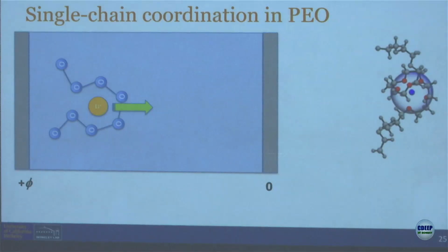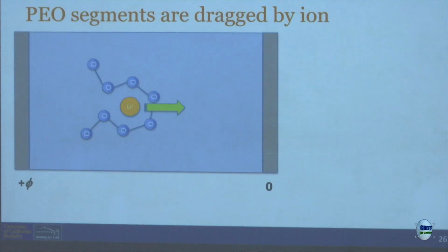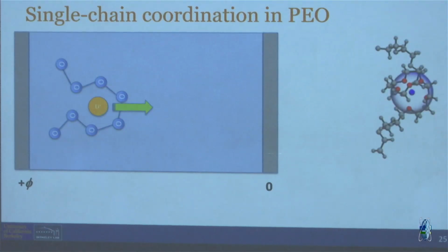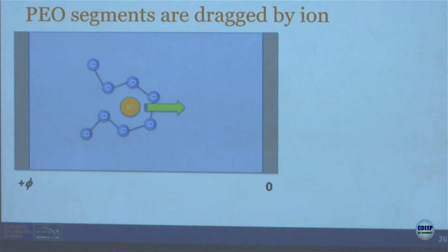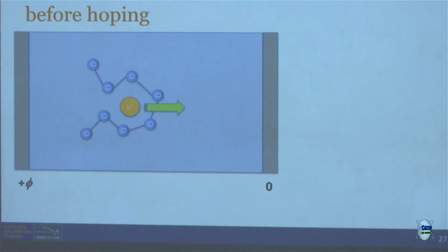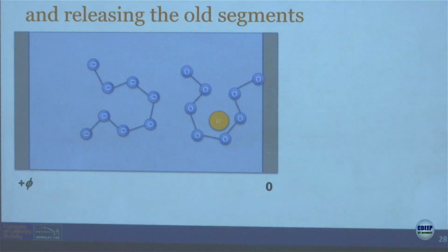The importance of solvation time is easy to draw in pictures, and that's what I'll show you. There's some potential, plus phi on one electrode, and we call it 0 on the right electrode all the time. You're allowed to do that. But you see, when the solvation time is large, as this lithium is moving, it's dragging the solvent with it. And then at some point, you get a fluctuation. The lithium ion hops and goes there.